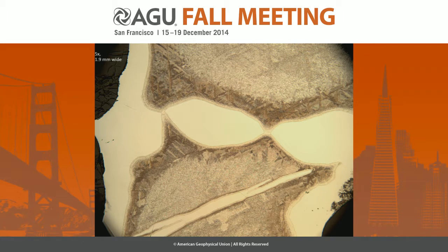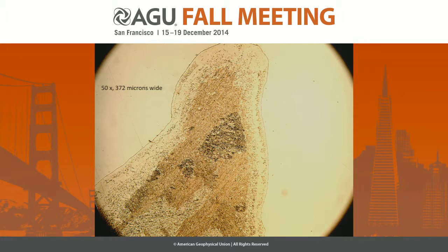We're looking at the metal phases of an Eagle Station Pallasite. It's been cut off, but this is at 5x magnification. At this length scale, it appears that the Eagle Station Pallasite metal resembles main group Pallasites. However, at higher magnifications, this is no longer the case. The cloudy zone taenite is heavily disturbed and only wispy remnants of it remain. The tetrataenite rim is also altered, and in the plessite field, we see evidence of spheroidation. Taken together, this is evidence for a shock heating that might have been up to 320 degrees Celsius.